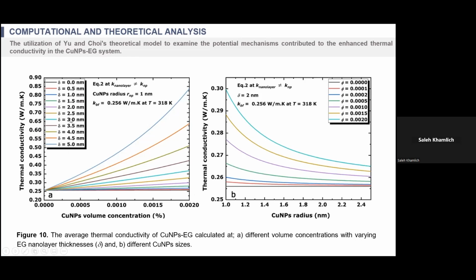So it shows clearly that the nanolayer around the particles contributes hugely to enhancing the thermal conductivity, particularly if the nanoparticle is very small, because this model works only if the nanoparticle is less than 10 nanometers. So here, by changing the radius or the size of the nanoparticles, it shows clearly that at higher size, even at higher concentrations, the thermal conductivity goes down. This means that you need tiny nanoparticles below 10 nanometers, which can really have high surface energy due to the surface to volume ratio, of course, because it's a nanoparticle, which can allow attraction of molecules to create this nanolayer, which can contribute to enhancing the thermal conductivity.